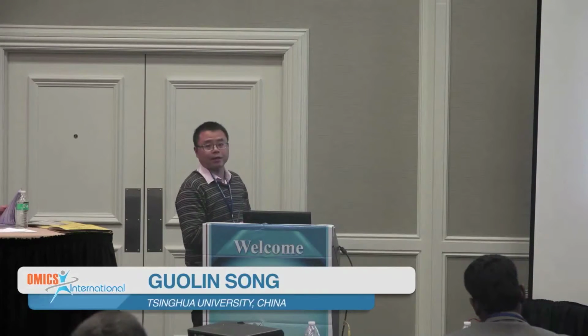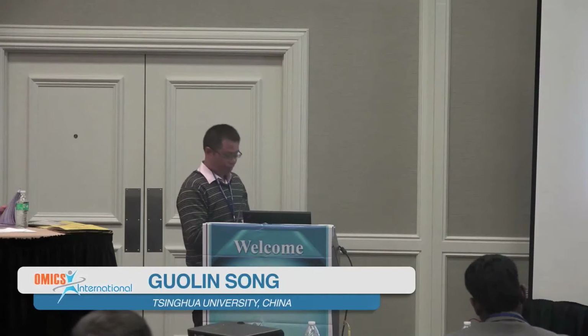And then we carried on our research. We wanted to look at the effect of adding different rates of 1% sodium chloride solution on the thermal behaviors of PCMs. Based on our research results, we can see that the peak temperatures and onset temperature show a sharp alteration of 3 to 5 degrees Celsius. The degree of supercooling has been reduced by 6 degrees, which is quite good. After adding the solution, the latent heat of the PCMs rose and became higher than that of octadecane, which is the pure PCM material.